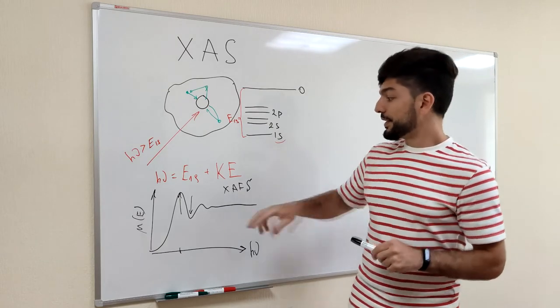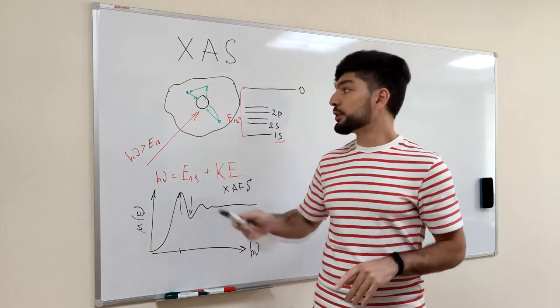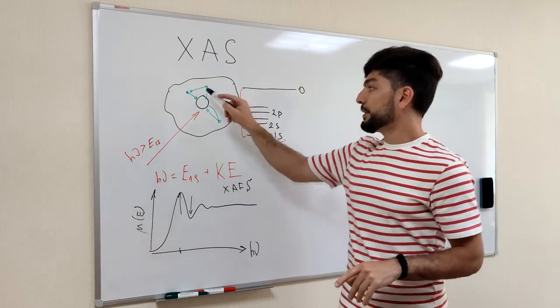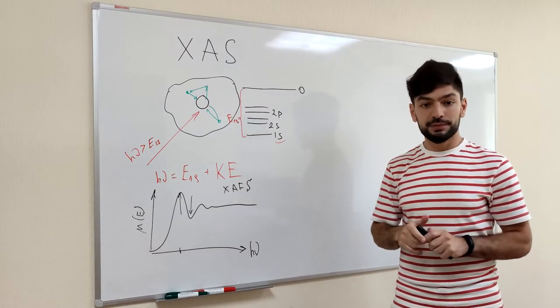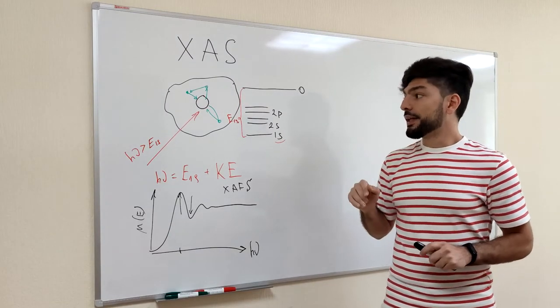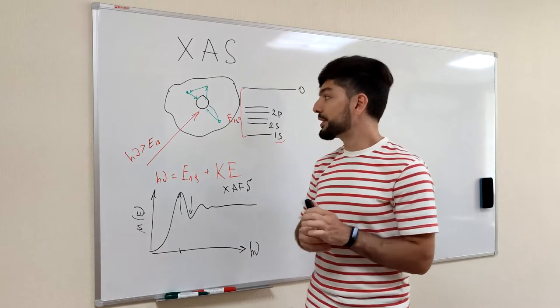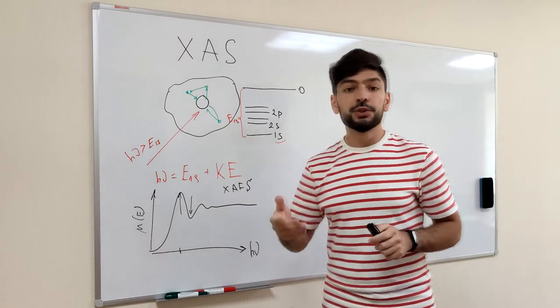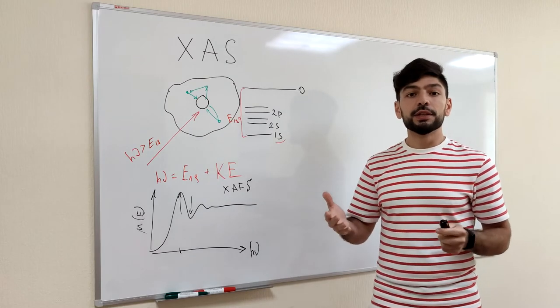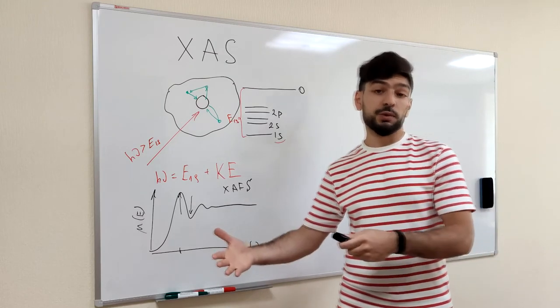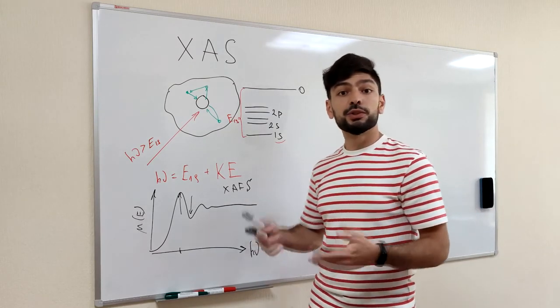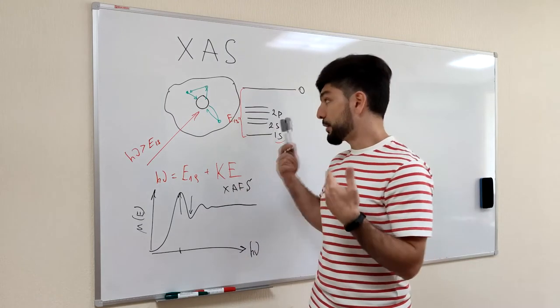Also, since the spectrum is a result of collisions from the neighboring atoms, this technique has local sensitivity. And due to this local sensitivity, you don't need a material to have a long-range order. So, your material does not need to be a crystal.